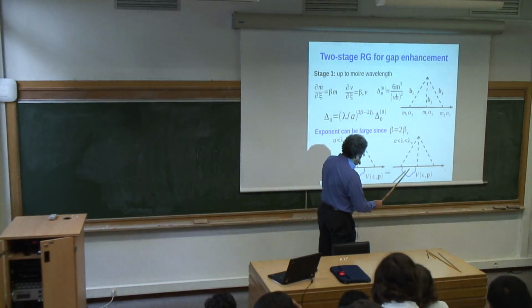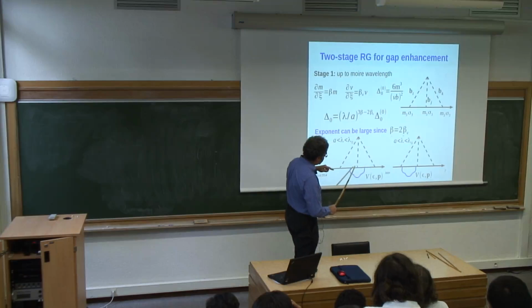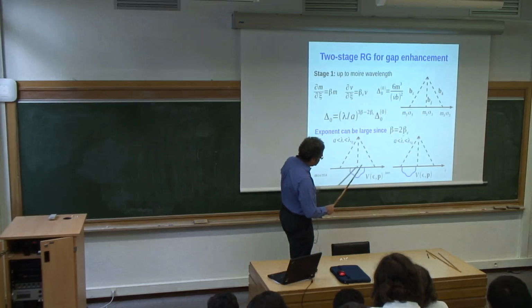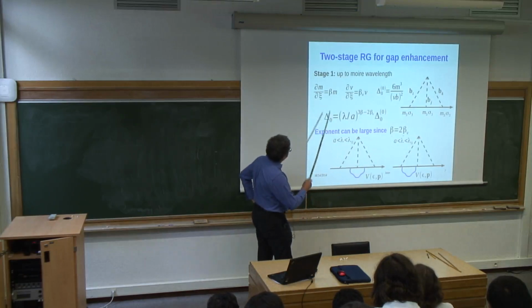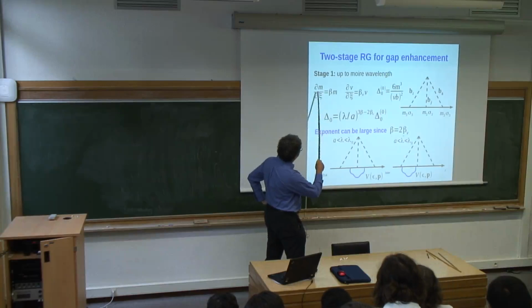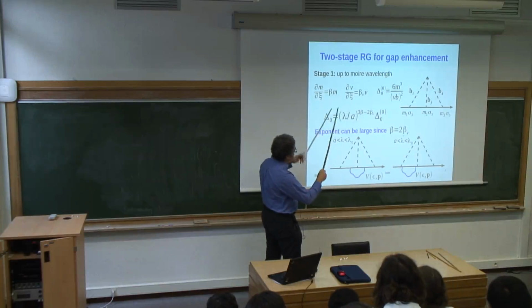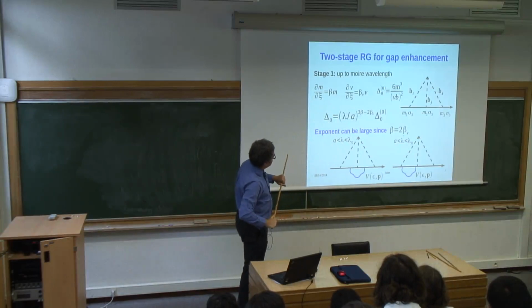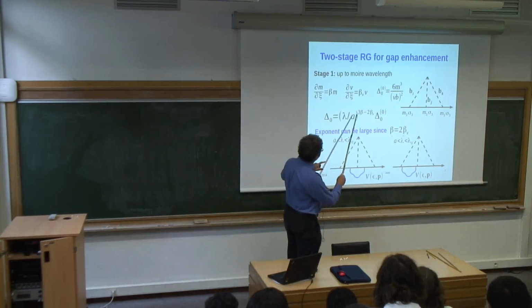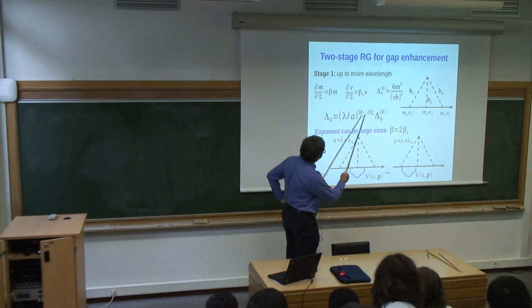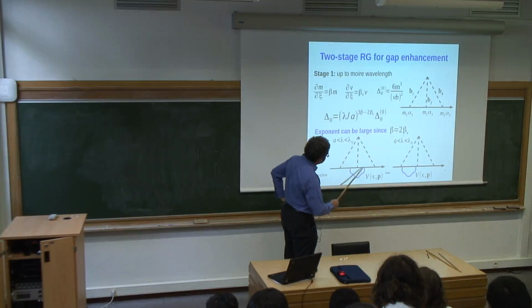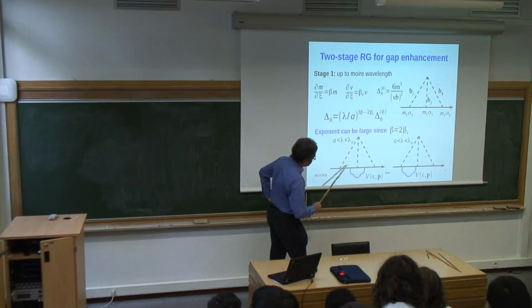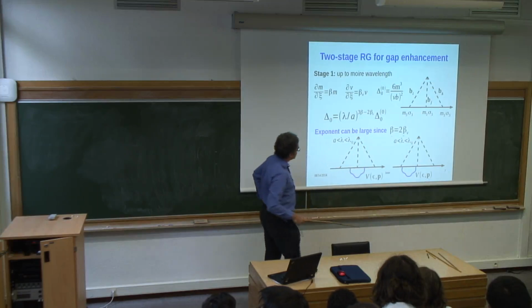log diverging contributions that will renormalize vertices, as we discussed before in QED spirit, also the Green's functions, and we have to put all of that together, and the resulting RG flow equations for mass and for velocity should be combined and studied together, and so the gap flows basically with the exponent which is 3 times the single vertex exponent for the mass, minus 2 times the single velocity exponent, and that arises simply from 3 vertices here and 2 Green's functions here.